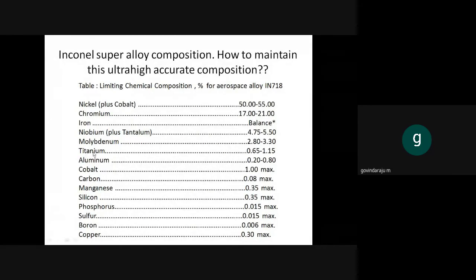Another example is titanium, Ti. The titanium problem is that whatever crucible you use, it will react with that crucible. See, there are only a few possible crucibles. That means if you want a 0.65% titanium alloy, you have to add a higher amount of titanium, maybe 0.8% or 1%. That too will vary dynamically. So each one has difficulty like this.